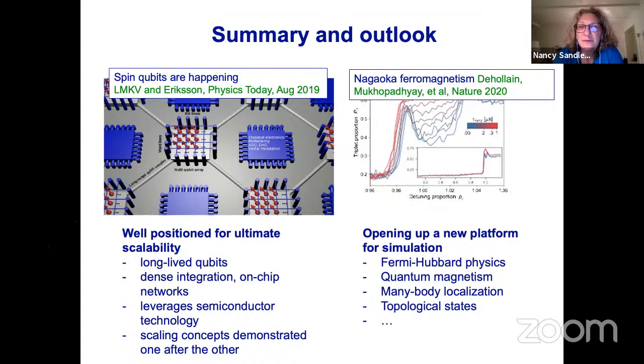So going back to the strong coupling regime that you implemented between the spin and putting a cobalt atom nearby. I have the picture that the cobalt magnet is a micron scale magnet. Okay. So my question is even more to the point. I imagine that you would like to do that for each spin, right? Which means you will need to have a lot of cobalt magnets nearby to each of them. Aren't they going to create fields not only for the spin that is nearby, but for the other one? So I am trying to picture the spacing and the screening, if you want, of the field, so you can make sure that you are attaching this inhomogeneous field to the spin that you want.